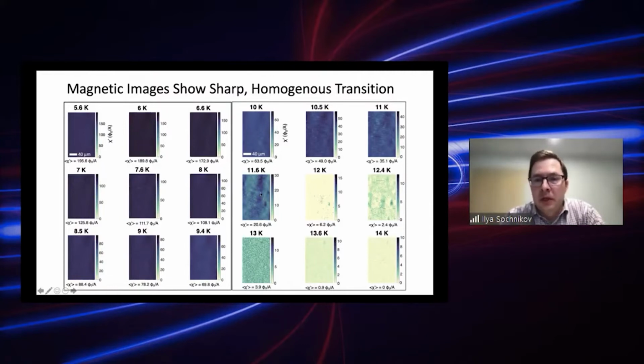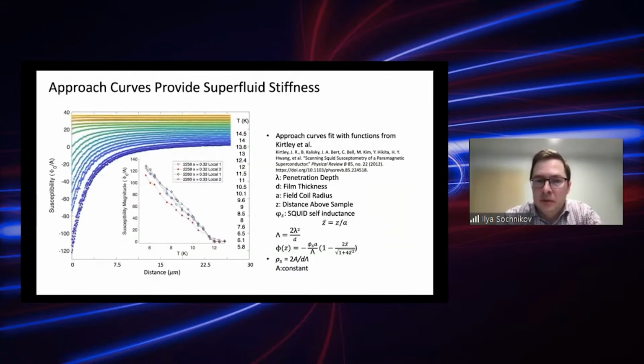So the critical transition temperature width is, as good as we can measure in our SQUID, below 0.4 Kelvin. Our thermometer is not exactly on the sample, so there's some uncertainty, but these are very, very sharp transition temperatures, and the quality of the uniformity is very comparable to single crystals. Actually, most of the non-uniformities come from the SQUID itself, from the way it moves, from the way it might be touching the sample. So there are artifacts predominantly from the measurements themselves. And we've confirmed these observations on a number of samples.